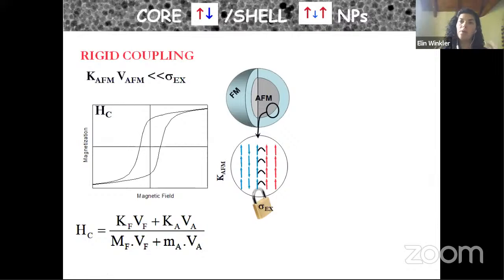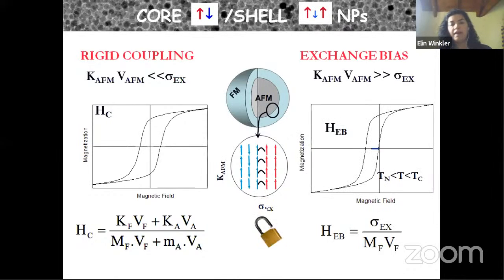But in this core shell system, we could find another situation. In the case that the coupling at the interface is not so strong, with which value can we compare that energy? Well, in that case, we compare the coupling energy, the exchange energy, with the anisotropy of the hard magnetic material, of the antiferromagnetic phase. So in this case, if this anisotropy is much larger than the coupling, we will invert the magnetization of the ferromagnetic one. Yes, the red spins in this case, we will invert those spins, but the antiferromagnetic phase will remain unchanged.